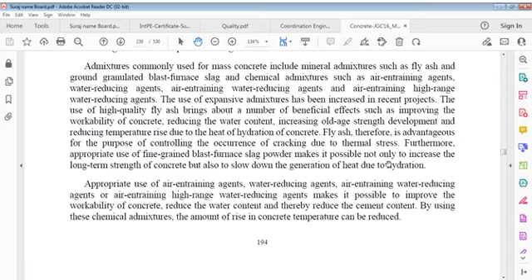Admixtures commonly used for mass concrete include mineral ones such as fly ash and GGBS, or we can say ground granulated blast furnace slag, and chemical admixtures such as air entraining agents, water reducing agents, air entraining water reducing agents, and air entraining high range water reducing agents. Use of these admixtures has increased in recent projects. Use of high quality fly ash brings about a number of beneficial effects such as improving workability of concrete, reducing water content, increasing old age strength development, and reducing temperature rise due to heat of hydration of concrete. Fly ash therefore is advantageous for the purpose of controlling occurrence of cracking due to thermal stress.